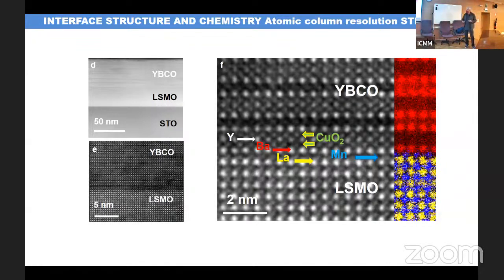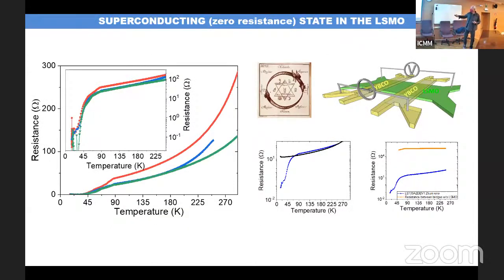We measured one of these devices: we inject the current across the YBCO and measure the voltage in the manganite. In the normal state, we get the typical shape of a manganite, but there is a clear superconducting transition, right? And when we look at this in a log scale, there is an orders of magnitude decrease of the resistivity, as it should. So we did endless control experiments to rule out artifacts like shorts between the YBCO wires.